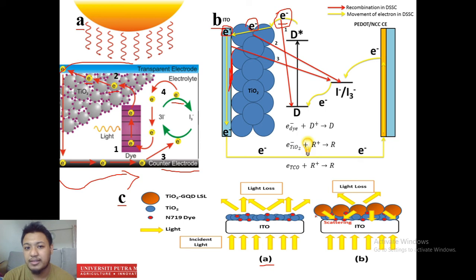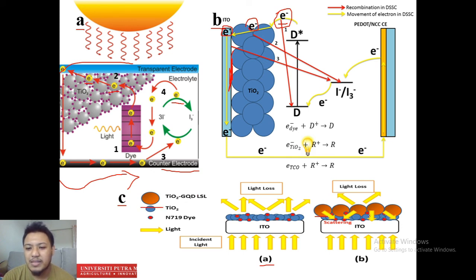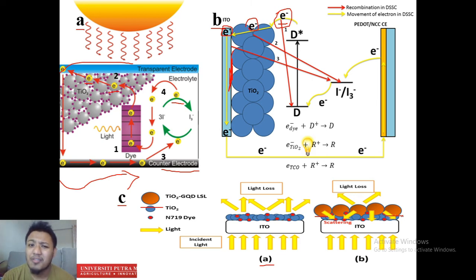To address light loss, a larger particle layer — a TiO₂ light scattering layer — is introduced on top of the TiO₂ mesoporous structure. Studies have shown that larger TiO₂ particles on top of the mesoporous structure block some incident light and this extra energy excites more dye molecules, giving higher dye-loading capacity, higher current, and higher voltage. However, it's tricky — not everything bigger increases efficiency. The size must be controlled: beyond certain limits, it creates resistivity, increasing resistance and dropping performance. It's a double-edged sword.